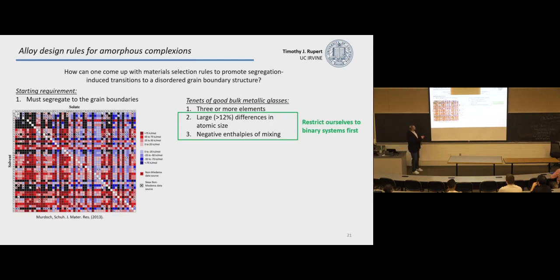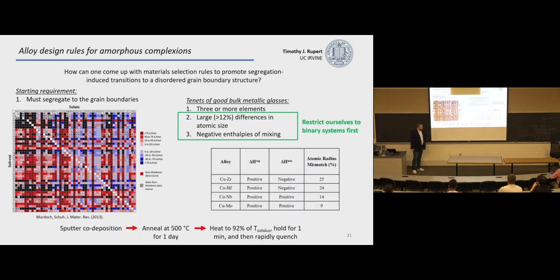As good scientists, you notice there's lots of things here and you want to decouple them. So we're going to first start by restricting ourselves to binary alloys. Which means we're going to forget this for a second. We'll come back to it in a little bit and just look at these two features. So I'm going to show you, we went and made nanocrystalline copper alloys, copper zirconium, copper hafnium, copper niobium and copper moly. And the idea was that if you look at these rules, you would predict that these top 2 would form amorphous grain boundaries, and these bottom 2 would not.